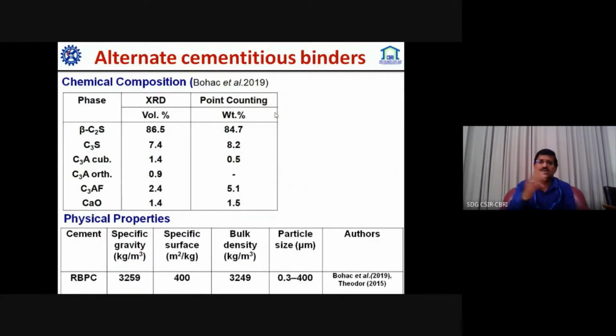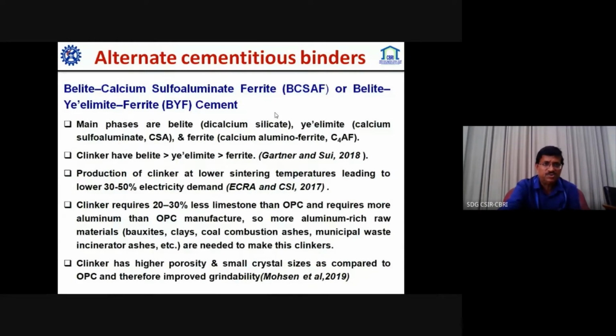So this is some study people have carried out. I have tried it because our work is going on in this area. And overall, if you look at the cement, its specific surface area is a little bit higher, but other things will be the same all the way. So that is important. And another is the belite ye'elimite ferrite, BYF cement. So these are the cements which are being utilized, with clinker calcination about 30% lesser, and it has a rich alumina content. And by this way our grindability, or energy requirement in grinding, will get reduced.